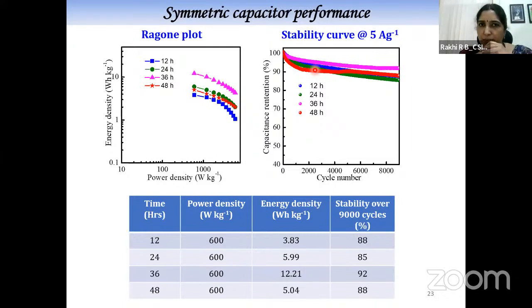Then we drew the Ragone plot and found that at a constant power density of 0.6 kilowatt per kilogram, our sample gave 12 watt-hour per kilogram, which is comparable with any state-of-the-art commercial level supercapacitor. So this material delivers its performance. And that is the direct growth.